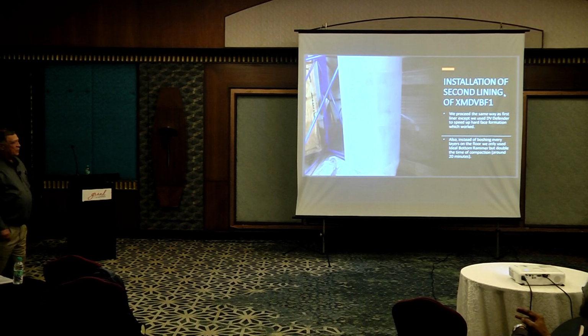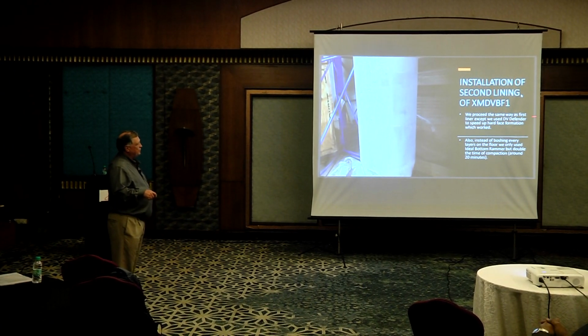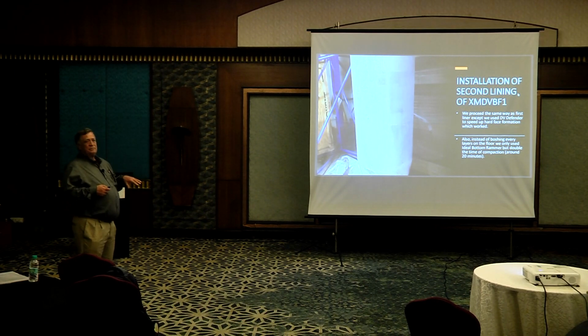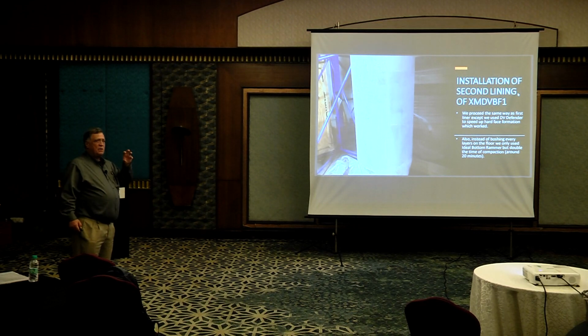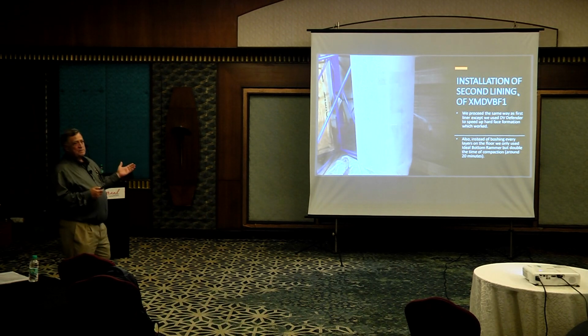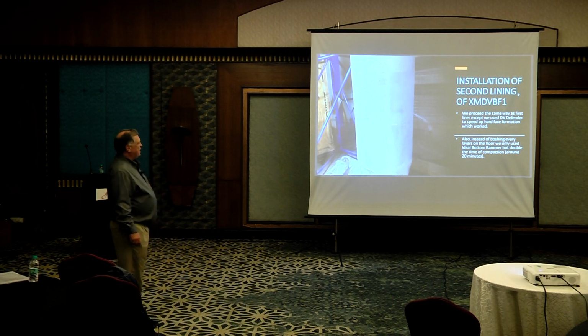So now we went to the second, and they wanted to find a way they could control the sinter a little bit more without adding boron oxide, of course. So Allied has a product, it's here, it's called DV Defender. DV Defender is a paint, and you paint it on your former, and you let it dry overnight, and then you do the installation of your silica just like you would normally. But during the sinter cycle, this is a very low melt temperature coating that seals the silica, seals the porosity of the silica. So it makes it a little bit easier to sinter a furnace. And we thought that if we tried this, this may eliminate the peeling that we had, those issues. So instead of bashing every layer in the floor, we only used ideal rammer, but doubled the time of the compaction.